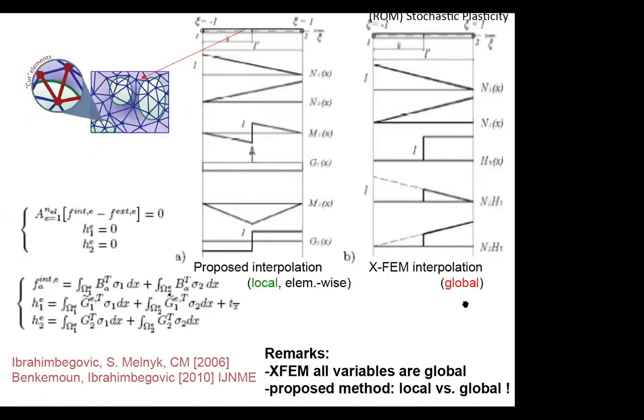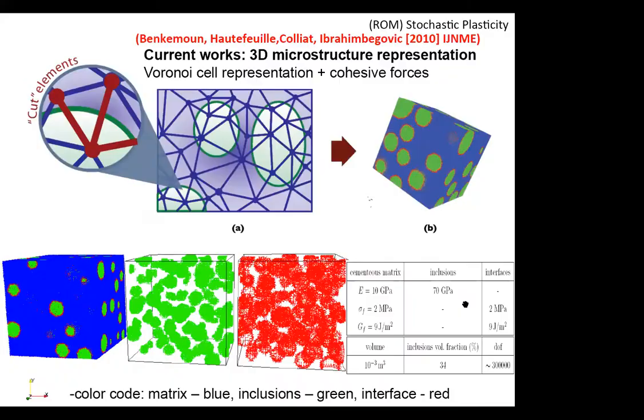So what this model can do, first of all, is the following. From one realization to another, you move the aggregate to different locations because this is how you build concrete. You're doing a mixture, so aggregate goes a little bit to the left, a little bit to the right. But if you want to be comparing different computations with different realizations, your mesh has to remain fixed. You cannot be changing the mesh. Otherwise, you will have an error in the mesh representation. So what is important is to keep these cohesive links from one realization to another the same, and the aggregates, the white spheres, go left and right.